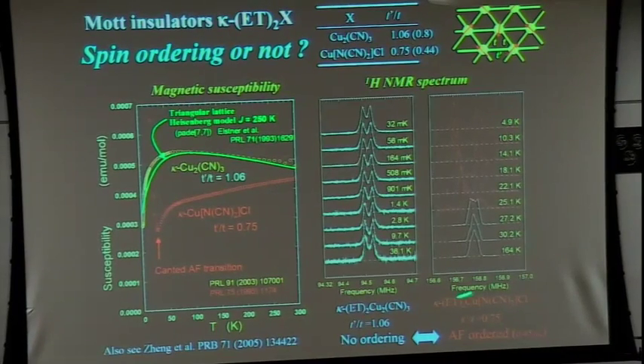This is the proton NMR spectrum, and this is the magnetic susceptibility, spin susceptibility, of two materials. This is the less frustrated case, the deformed triangular lattice. It shows weak temperature dependence, but you see an abrupt jump of susceptibility around 30 Kelvin or 25 Kelvin, a clear indication that some magnetic transition occurs. However, the triangular lattice material does not show any sharp anomalies down to the lowest temperatures, 2 Kelvin in this case. So there seems to be no magnetic transition in the spin susceptibility.